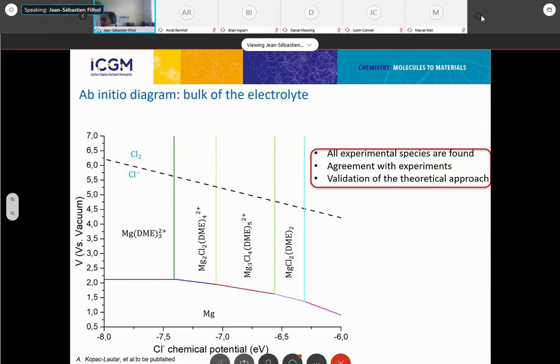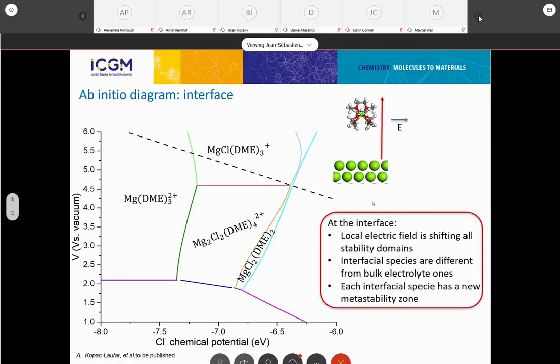But the bulk electrolyte diagram is not really interesting to understand the electrochemistry, because in fact what you need is what is happening on the surface. So we need to really build the surface Pourbaix diagram. And in this case, we see that the Pourbaix diagram is really changed because of the very strong electric field at the interface. And in this case, the active species at the interface are not the ones of the bulk.